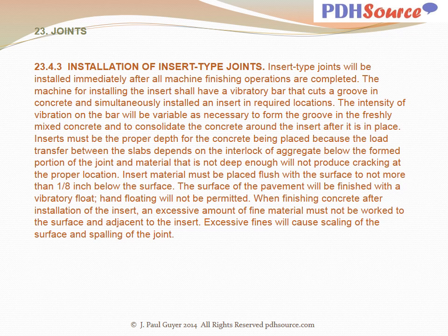Inserts must be the proper depth for the concrete being placed because the load transfer between the slabs depends on the interlock of aggregate below the formed portion of the joint, and material that is not deep enough will not produce cracking at the proper location. Insert material shall be placed flush with the surface to not more than 1/8 inch below the surface. The surface of the pavement will be finished with a vibratory float. Hand floating will not be permitted.